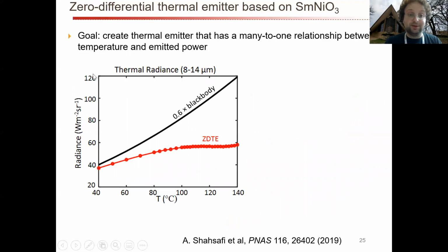And so if you take a look at the radiance, integrated over all wavelengths versus temperature, you can see that the blackbody is going to increase with temperature as expected, but the zero differential thermal emitter has a very constant curve. The slope is zero, and therefore, no matter what temperature you're at within this maybe 100 to 135 degrees Celsius region, your radiance is the same.